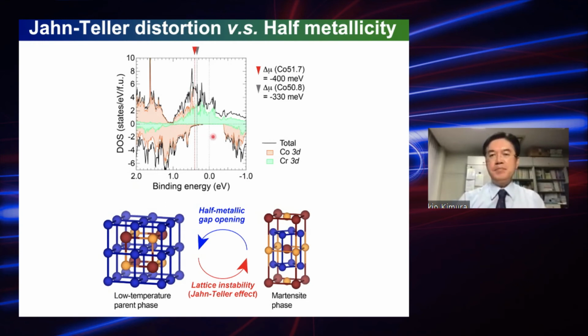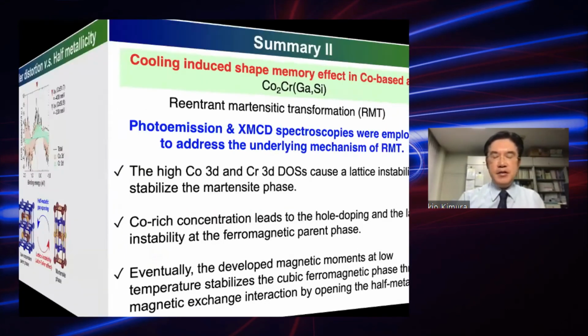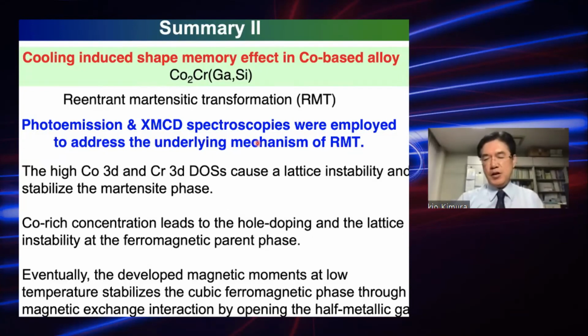But at low temperature, the magnetic moment is actually developed. That helps to get the half-metallic band structure, as you can see here. This may be the reason why the reentrant martensitic phase transition occurs for this sample. Actually, there is a competition between the half-metallic band structure and the lattice instability due to the large density of states peak at the Fermi energy. Probably that may be the reason why you have a cooling-induced martensitic phase transition down to the cubic phase.